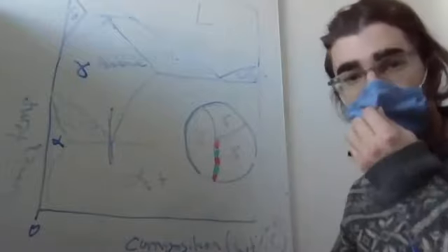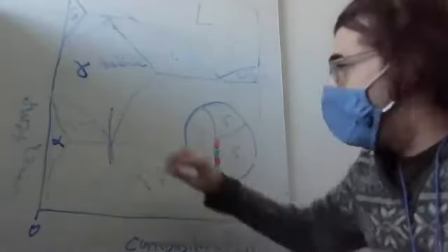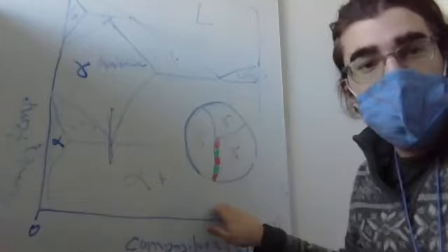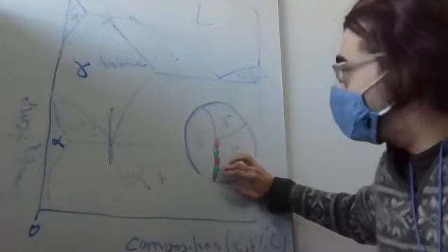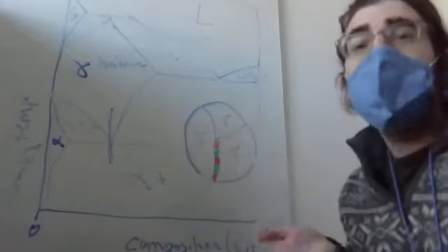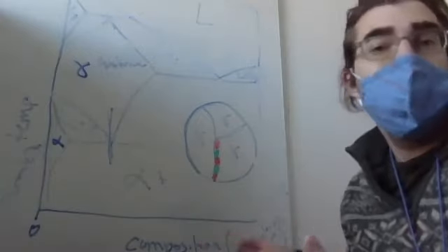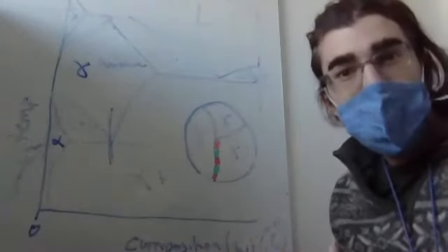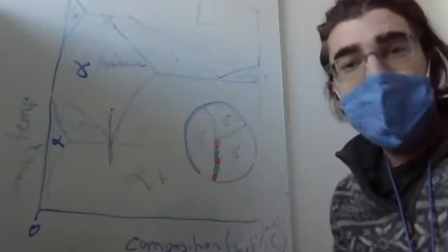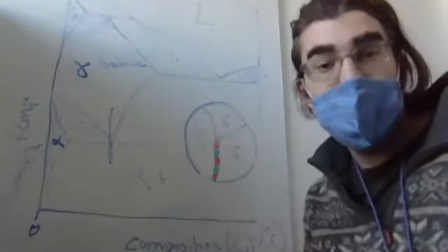So along the grain boundary, as we cross the temperature threshold into this alpha plus cementite domain, we're going to have a segregation occur where the carbon is going to diffuse. And why is the carbon the thing that's moving here? Well, carbon is an interstitial, right? So it's not taking up the lattice spaces of iron. Carbon is small, so you have a small interstitial with lots of positions for it to move. It's low energy for it to move. So the carbon is really going to be driving this transformation.